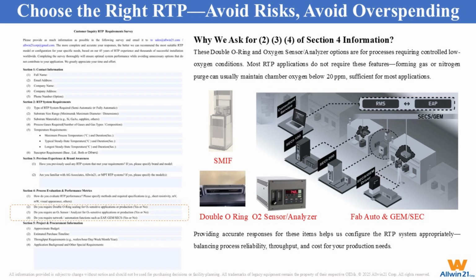Double O-ring sealing enables pre-process oxygen leak checks. Run stop automatically if oxygen exceeds the threshold, protecting expensive wafers. Oxygen sensor/analyzer continuously monitors oxygen during processing, halting the run if instability is detected to prevent scrap. Tighter oxygen limits may reduce throughput due to extended purging and monitoring. We recommend determining oxygen requirements via a simple U-curve evaluation. 20 ppm suffices for most applications, though the AccuThermo AW series can achieve 10 ppm or 5 ppm if necessary. For R&D or low-volume users, these features are generally unnecessary unless budget is not a concern.